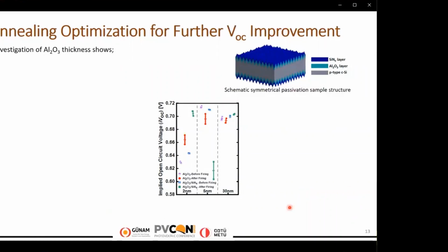For further improvements on VOC, symmetrical passivation structures were fabricated to mimic the rear side of the homogeneous emitter PERC structure as shown. First, the aluminum oxide thickness is varied from 2 to 30 nanometers, applying a two-step activation anneal in the case of all the produced solar cells up to now. And implied VOC results show the maintained high passivation levels of 30 nanometer thick aluminum oxide is because layers with these thicknesses can themselves provide the hydrogen necessary to achieve chemical passivation of the silicon surface.